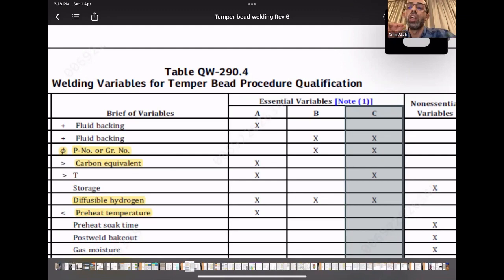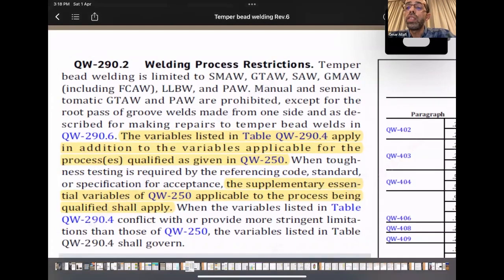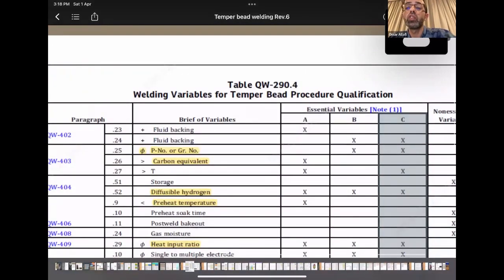The answer is no, simply because, as I said earlier, these listed variables apply in addition to the variables of QW-250. So I'm giving this example just to emphasize that although it is not an essential variable here, it is an essential variable in the original or basic WPS qualification in QW-250. And that's why that doesn't mean that you can use this technique for different P numbers.